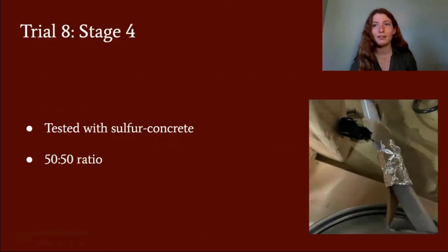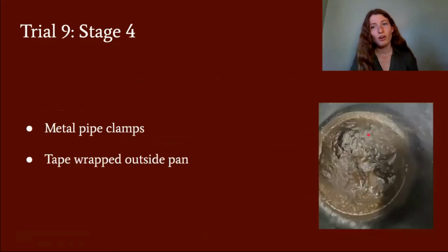However, almost immediately, the pump came totally out of place because the tube clamps that I had been using were made of plastic and got melted through by the tape. So I replaced them with metal, and this time I eliminated the tape from inside the pan because I was trying to eliminate any extra variables that might move things around. So you can see here, it was kind of thick though, and it also did not work. And it really was kind of clumpy in the center.